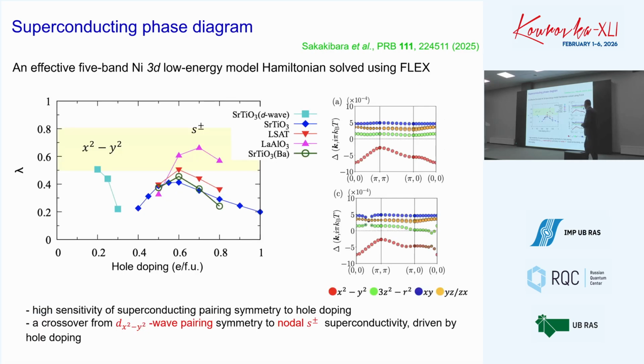So, probably one of the last slides on this system, with somewhat different methods. Many different approximations were used to show that, in principle, near optimal doping this is possibly x squared minus y squared wave superconductivity, similar to cuprates in some respects. Although at high doping and with some fine tuning, we can reach s plus minus superconductivity. It's multi-Fermi: you need to have several sheets on the Fermi surface. This is somewhat similar, I find, to iron-based superconductors.